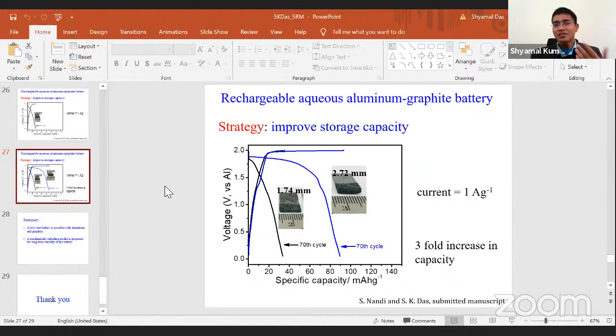So the increase in capacity values is very important because that's what will define your energy density. With time, what we have seen is that if we use the battery for a longer period of time, there is an increase in the capacity. It is because we are using graphite, which is a material stacked with graphene layers. Initially, it is very difficult for aluminum ions or any kind of ions to intercalate in these layers. But once it intercalates, the expansion between the graphene layers increases. When it increases, ions can very easily move inside this structure.